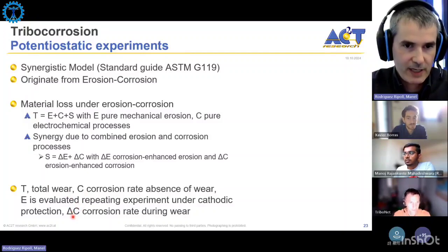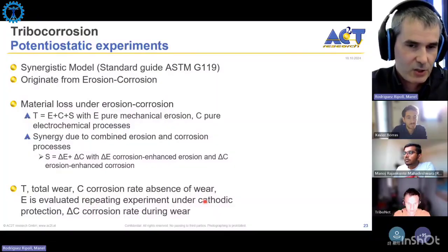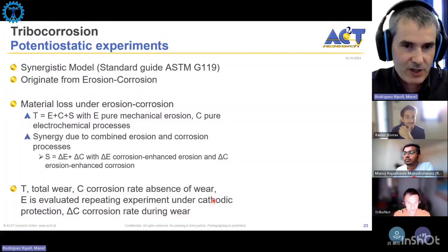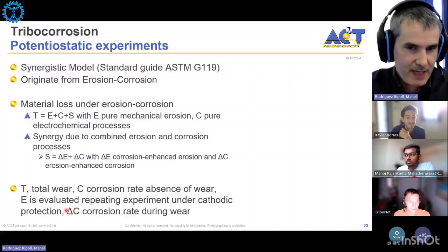Because if you want to get, for example, pure mechanical wear, then you apply cathodic protection, but it's known that depending on the cathodic potential that you apply, you may change the wear rate. So then which is the correct wear rate? Because depending on the cathodic potential, if you start, for example, generating hydrogen in the cathodic reaction and your material is sensitive to hydrogen embrittlement, you will change the wear. And therefore, it's not very well defined what this pure mechanical wear means, just by applying cathodic protection. So you can change it depending on which potential you apply.